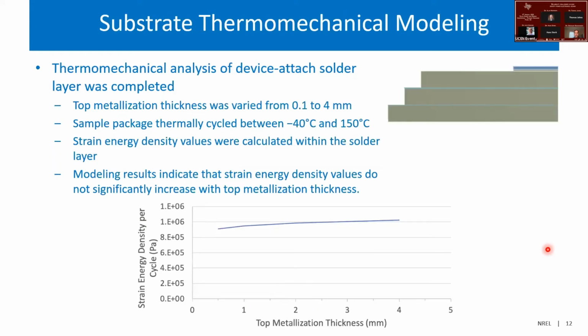On the thermomechanical reliability aspects, the strain energy density per cycle as a function of top metallization thickness. This top metallization thickness, it's important to increase just from a thermal perspective. It is beneficial, but what happens to the thermomechanical behavior and reliability? So fairly flat line here, so not much of implications from a reliability perspective is what the key point here is.